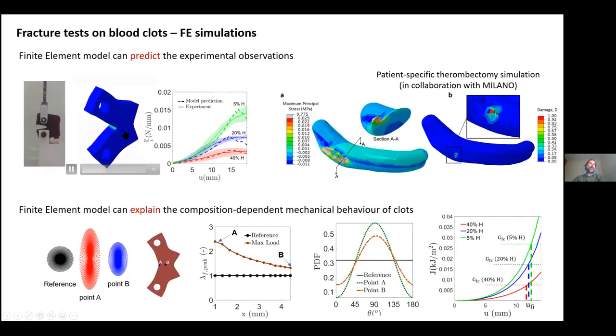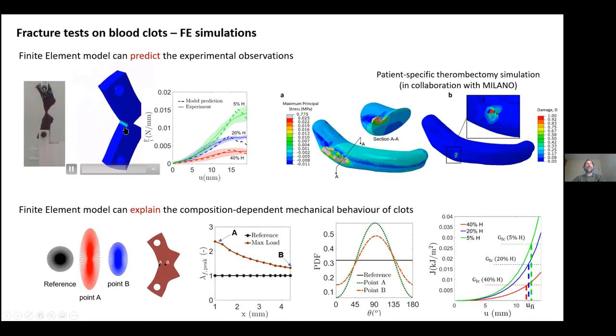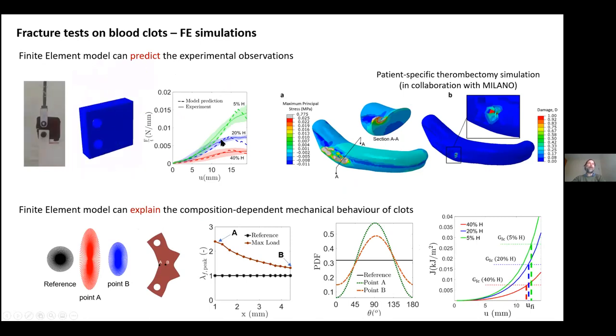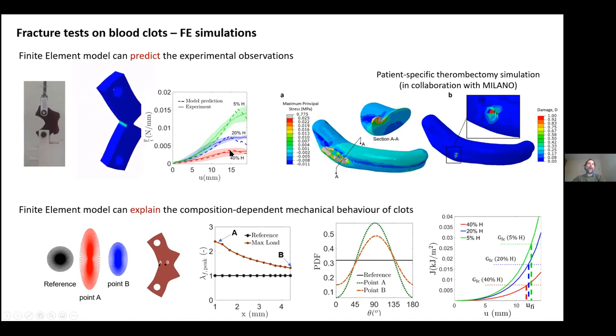And this is our finite element analysis with a cohesive zone model of the propagation of the crack in the clot. And we're able to get a very good match with the experimental data as a function of the fibrin content. And again, our finite element model is telling us that we're getting big alignments of the fibrin network just behind the crack tip, which is giving us a high degree of toughening. So we then worked